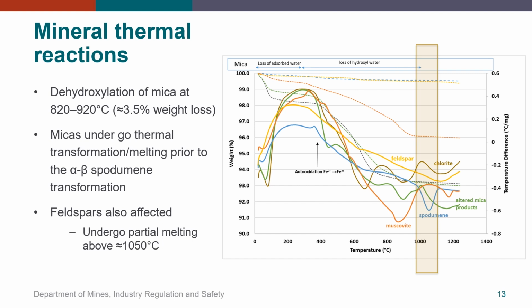The graph on the right shows the loss in weight as the dashed curves and thermal reaction curves as the solid lines of various minerals in pegmatites against the temperature on the x-axis. As you can see, the primary muscovite and the altered mica products, or cookeite, undergo dehydration and melting reactions at temperatures just before or coincident to the zone of spodumene transformation, shown by the shaded box here. Feldspars may also be affected and can undergo partial melting above about 1050 degrees.